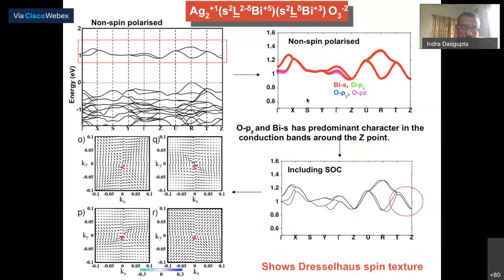So this is our final system, again having the same symmetry. Again I look at the Z point, and what I figure out for this compound is that we have a Dresselhaus spin texture. And again, if I look at the character of the conduction band, it is of bismuth s and oxygen pz character.